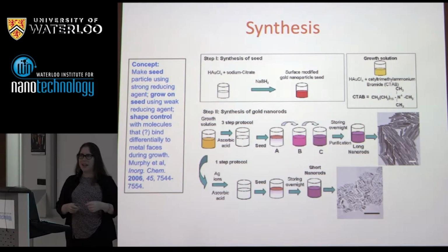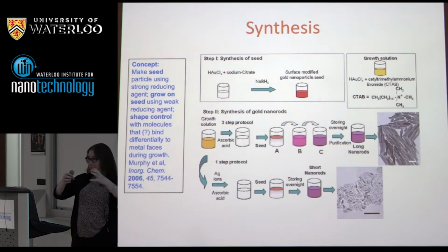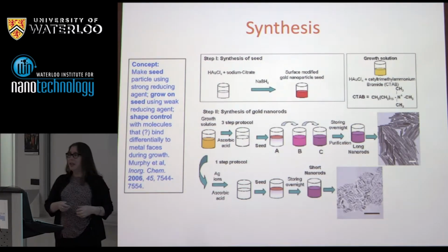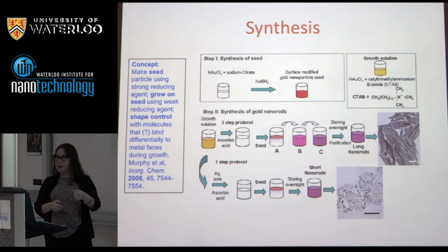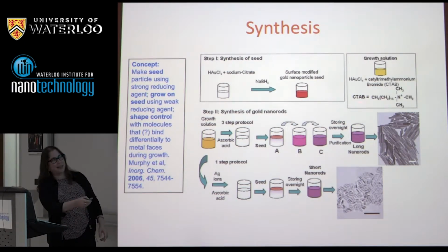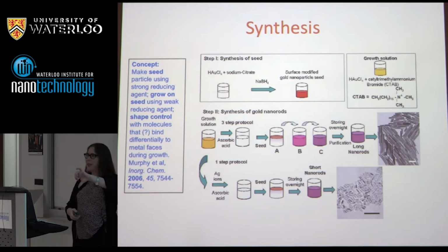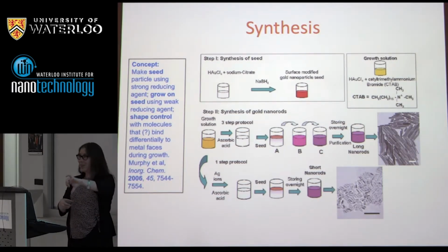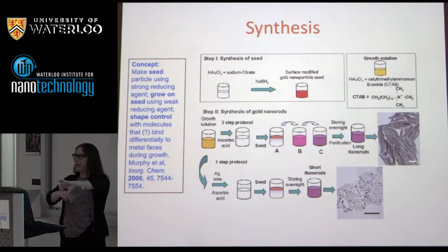Now, if you do what I just said with nothing else, you're just going to get bigger and bigger spheres at some level. So what we need is something else in the pot to direct the growth, and that's what this surfactant stuff is here. It's CTAB, so cetyl trimethylammonium bromide. Cetyl's an old name for a 16-carbon chain. There's the trimethyls. This thing makes rod-like micelles in water by itself, which was our original idea, which turns out to be wrong, that it would be like a soft template.